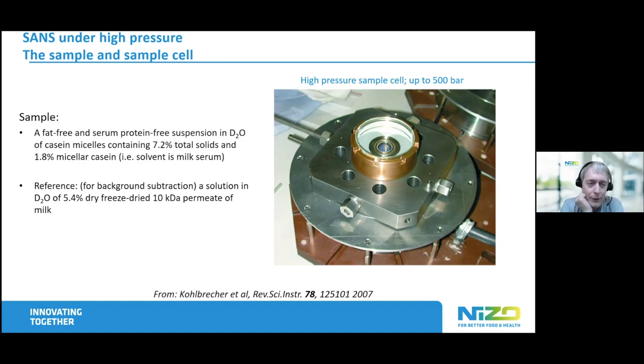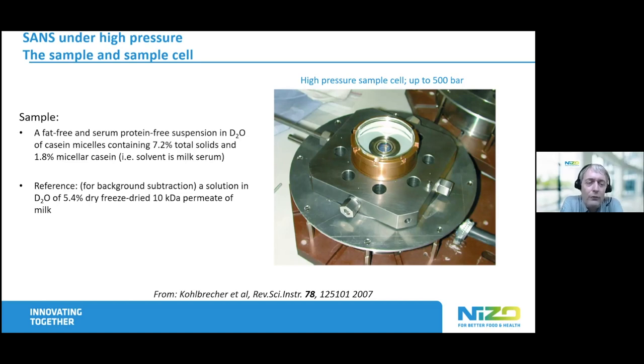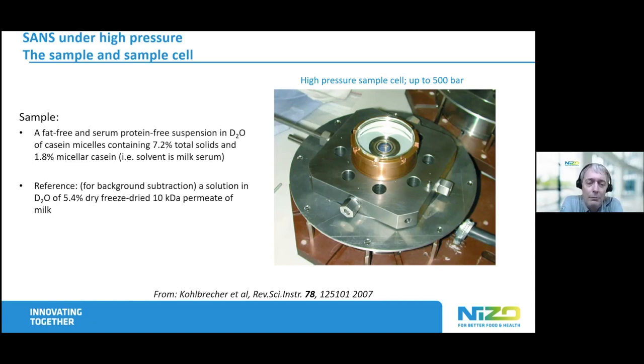We took as a solvent a solution of milk serum — we collected milk serum by ultracentrifugation, freeze-dried it to get a powder, then re-dissolved it in D2O. Then you have a solvent which looks a lot like milk serum. It also gives you the proper reference — the same system of milk serum without the micelles.